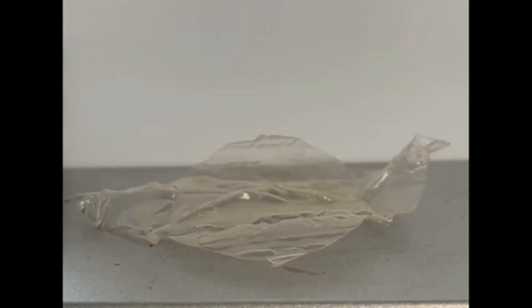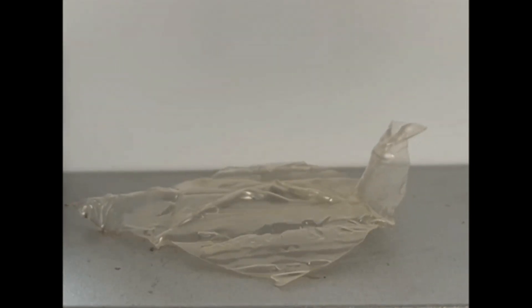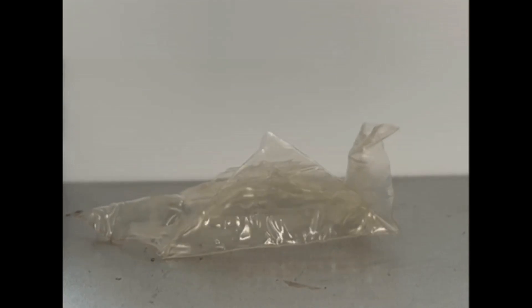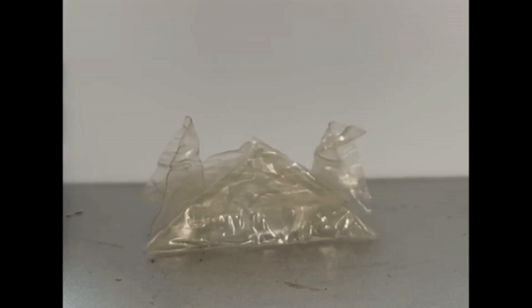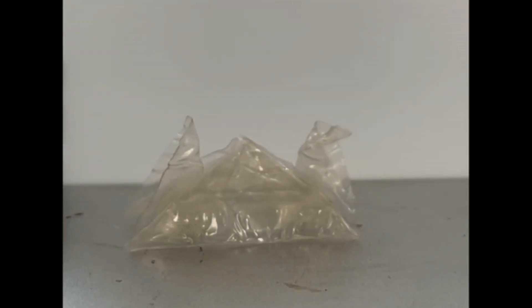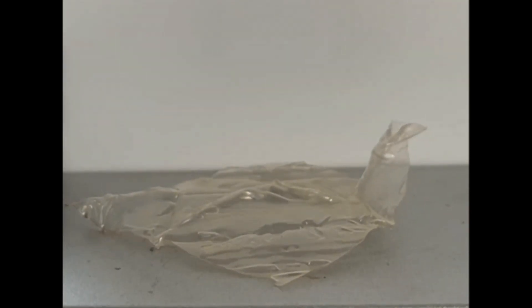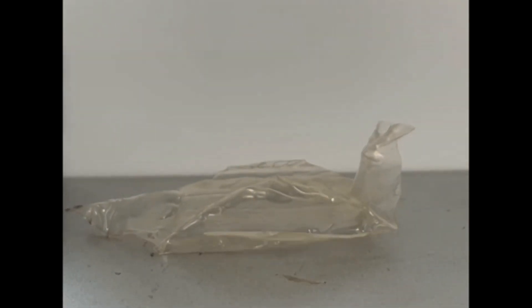VPR is over 5 times as resistant to breaking as a typical epoxy resin vitrimer. It also repairs itself 15 times as fast, can recover its original memorized shape twice as fast, and can be chemically recycled 10 times as fast as typical vitremers. It even biodegrades safely in a marine environment, which is new for this class of material.